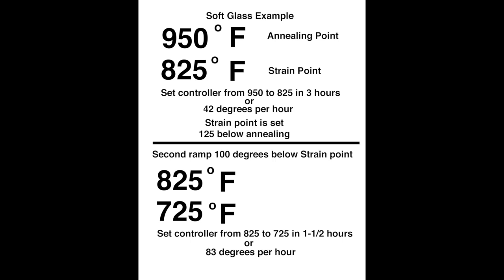And depending on the controller you have, I have 2 different ones. One is set with hours, so you just put the 2 set points, 950 and 825 in 3 hours. Or if you have a controller that uses degrees per hour, you would simply put these 2 set points and use 42 degrees per hour, and that'll give you approximately the same amount of time, 3 hours.